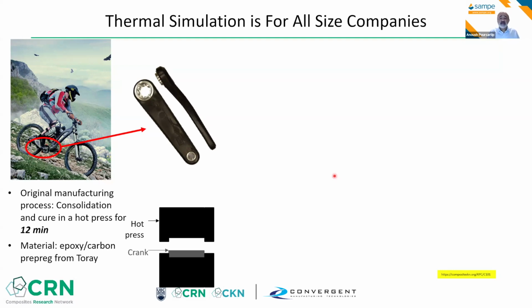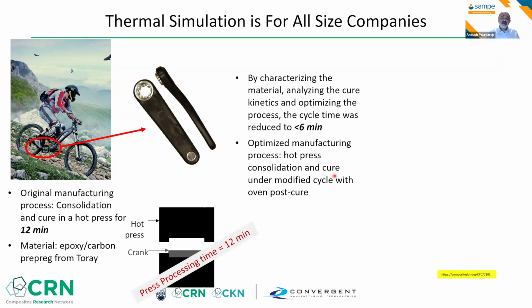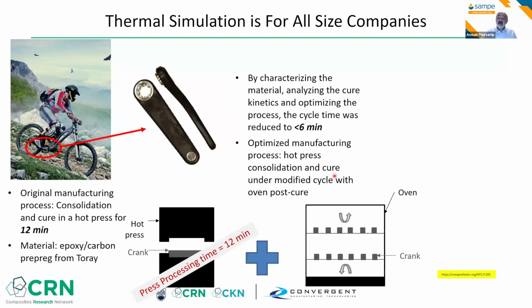So they came to UBC, and what we said was, can we use process simulation to help them? We made a very simple cure kinetics model of a tiny fraction of the effort that would have gone into, say, that airplane, the 787. And based on that, we were able to identify that the material was gelled and, in fact, vitrified within 6 minutes. So this was an obvious candidate for a cure plus post-cure approach. And all of a sudden, the process time was brought down to 6 minutes.